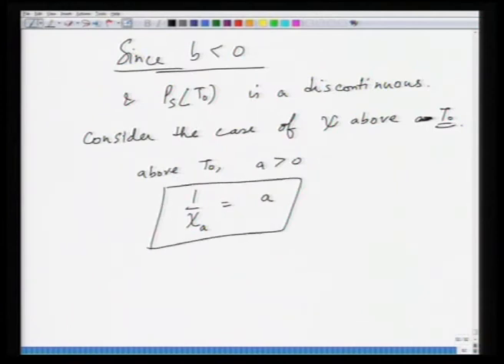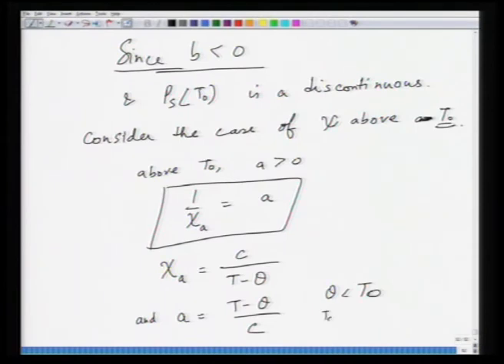This is a simple expression, so again it is in the paraelectric state, and chi A, as you know, is given by the Curie-Weiss law, so chi A becomes equal to a constant C divided by T minus theta, and hence A becomes equal to T minus theta divided by C. Here theta is somewhat smaller than T naught, and this is called Tc, so Tc is smaller than T naught.